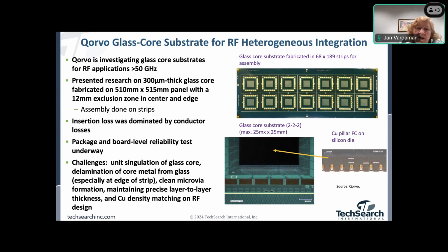Insertion loss really was dominated by the conductor loss. They said they've got package and board level test reliability underway, but they don't have any results that they can report. That glass core substrate had a 2-2-2 construction. Maximum would be a 25 by 25 millimeter body size because, for the RF parts, that's more of what you might need. And the copper pillars would be on the silicon die and it'd be attached to that.